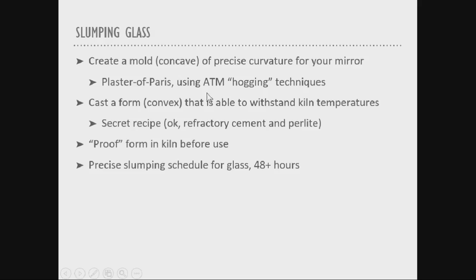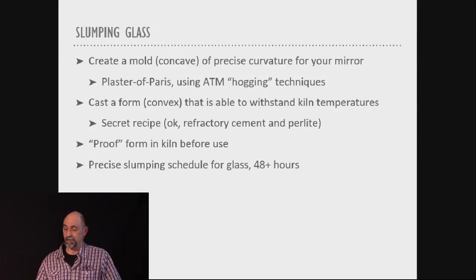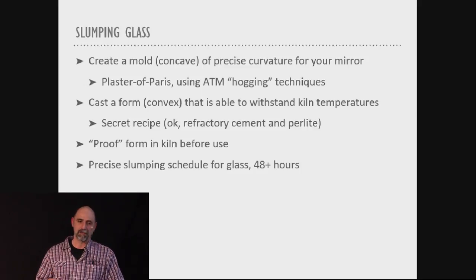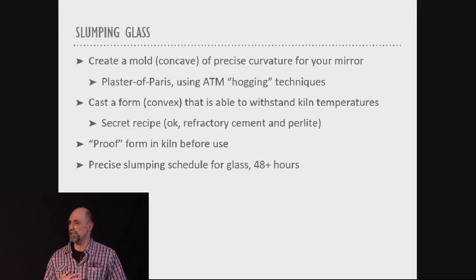Now the trick here is that this form has to be made of a material that's going to be able to withstand the temperatures of a kiln. And when we're slumping glass, we're talking about 600 centigrade, 650 centigrade. So you need special materials, and it's a secret recipe, but it turns out that the recipe is refractory cement and perlite. And you don't even have to use refractory cement. We've experimented with different grouts.